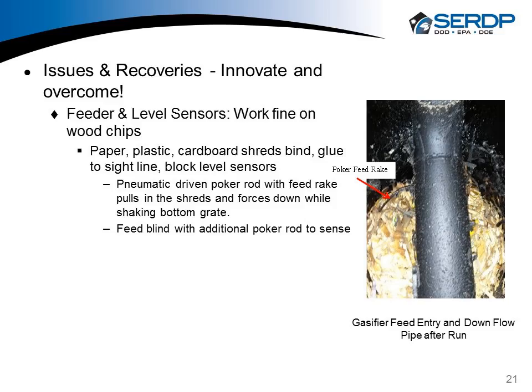Then we got everything together, we started running, and then of course the issues and opportunities to innovate and overcome the issues starts popping out of the woodwork. Our feeder and level sensors work good on wood chips, but when we had the paper and plastic, primarily the paper shreds, tended to blow around in the gas flow. And of course you got tar going all over the place, so they tended to glue to everything and block the line of sight for the level sensors. So we were kind of stuck running blind after the first day or so of operation.